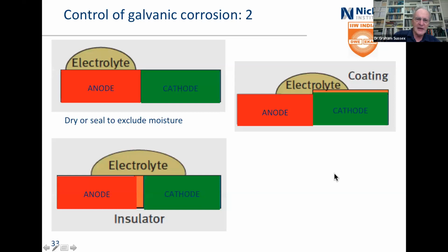Okay, back to the electrolytes. This is how you control galvanic corrosion. You make sure it's dry, or you exclude the moisture somehow or other. You make sure that you don't actually get moisture going between the two. You can put a coating, and it's shown here that you put the coating on the cathode. Well, now, why would you do that? Why wouldn't you stop the corrosion by putting something on the anode? Well, that's easy. If you get a small hole in the coating, then all of the corrosion concentrates on that point. And so you always coat the cathode.